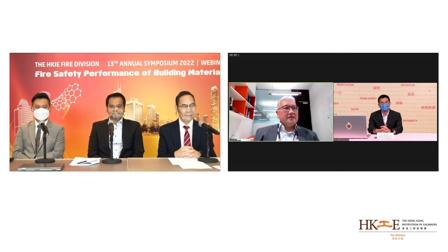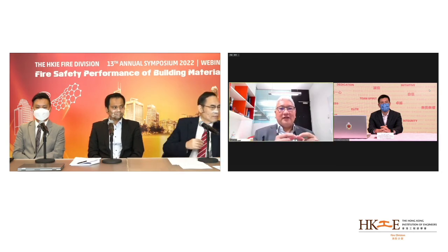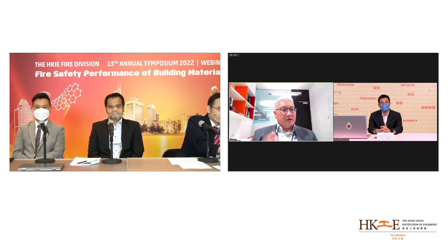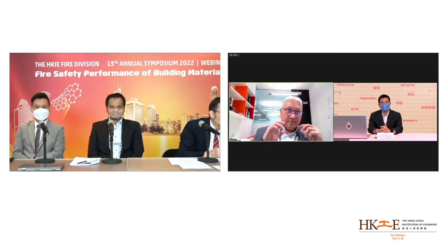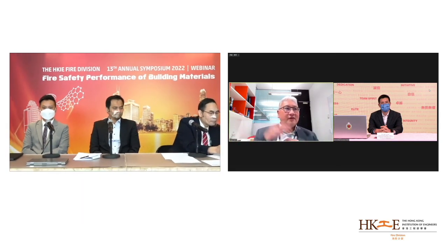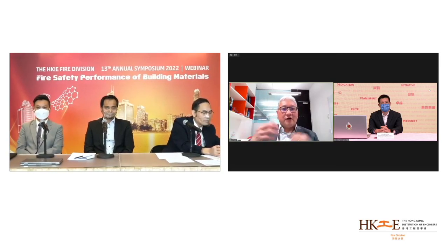In essence, nano clay is like a brick you shrink to the nanoscale. For MXene, it is titanium carbide that you shrink to the nanoscale level. Because it is a metal and also has a lot of good properties, we have found that MXene, which is a 2D nano sheet, if you can lay it in a systematic manner, actually forms a barrier. To make the barrier, you need a glue, and the glue part is chitosan.